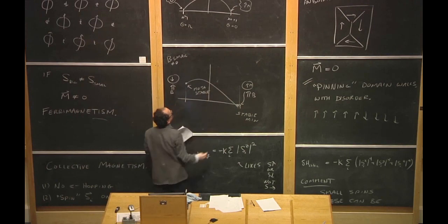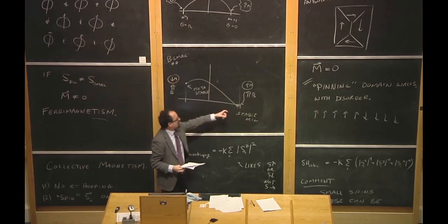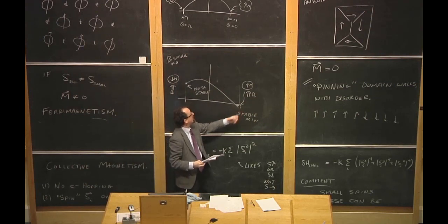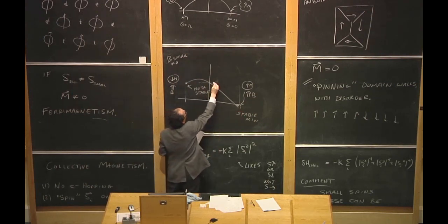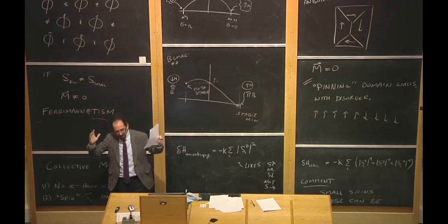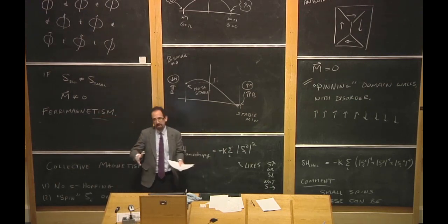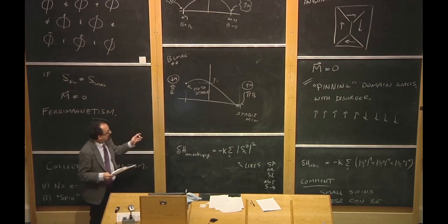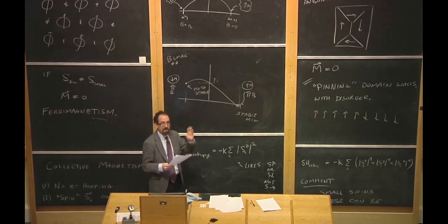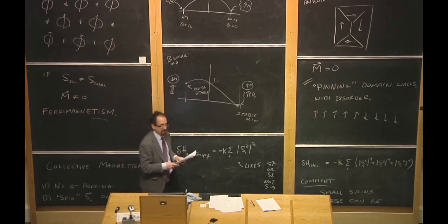In order to get from the metastable case of the magnetization pointing in the opposite direction as the magnetic field, down to here where it would rather be, it has to get over this activation barrier. And this means you have to take all of your atoms, maybe 1 million of these atoms, and somehow flip them all over simultaneously, either thermally or by quantum tunneling. And that's a process that's so difficult that at low temperature it may never happen. So you can have these little crystals of magnet have their magnetization stuck in the wrong direction.